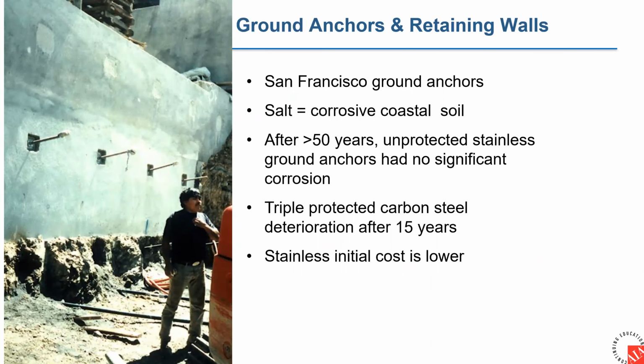This is a company in San Francisco that's been in business for several generations, three that I'm aware of. The grandfather, 50 plus years ago, had been required to use stainless steel as a ground anchor for walls near a dam. In the intervening years, the family went to using triple protected carbon steel. But when they went back to do remedial work or make changes in these walls, they were finding that it had begun to deteriorate after 15 years.